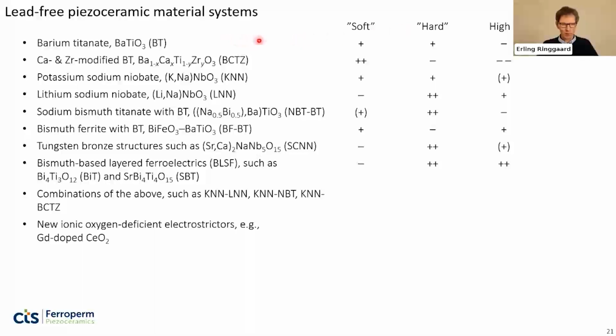So first, barium titanate. It's possible to dope barium titanate both to obtain soft and hard properties, different dopants, of course. But it will never be well suited for high temperature because the Curie point is close to 120 degrees C. Then a variant of barium titanate, which is modified with calcium and zirconium. You can get even softer than barium titanate. You'll generally find it difficult to get hard properties, and certainly it's not useful for high temperature because the Curie point is even below 100 degrees C.